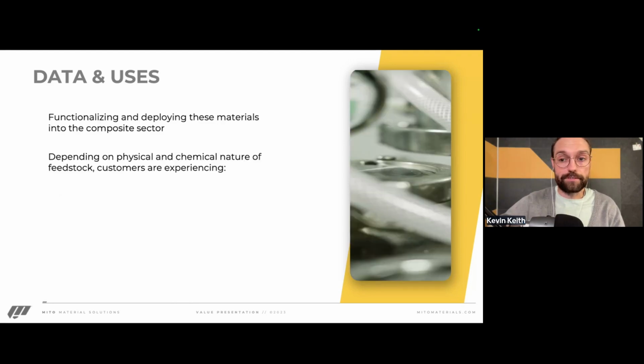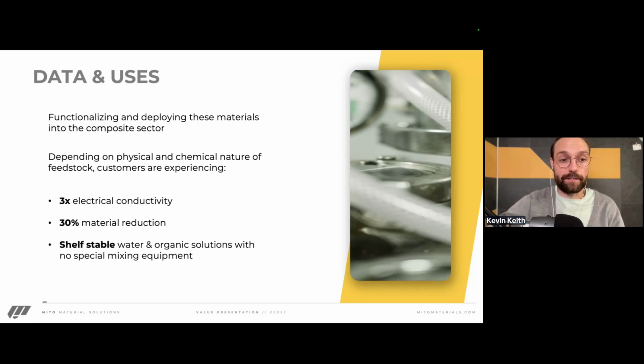Now, with these bottoms-up graphenes, Mito has functionalized on top of them. And what we do within these composite materials is that we look at certain systems, whether it's a polyester, polypropylene, or epoxy system, and we're able to fine-tune, functionalize on top of, and deploy these materials to create some really wild characteristics. So, depending on the physical and chemical nature of the feedstock, our customers out in the field are experiencing 3 times electrical conductivity increases.